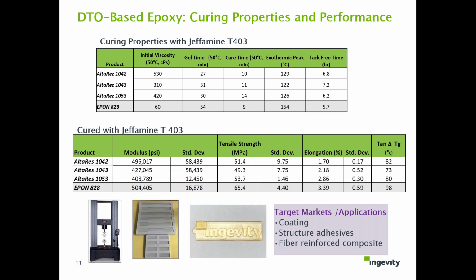The reason for that is the higher peak exothermic temperature generates higher internal stress and causes some micro cracking. Under pressure, there are potential problems. So this potentially may have some benefit for this type of application. Now, the last column is coating properties. The tack-free time, compared to benchmark, is pretty similar. So epoxy people are also interested in thermal and physical properties.